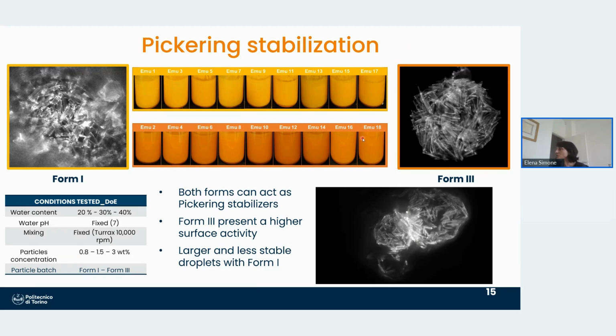And then again, Julia, now she's at the University of Leeds with a collaborator of mine in the physics department, Dr. Poncevic, and we're using light sheet microscopy to look at the position of the crystals at the interface. Form 3, as you can see, has a very nice affinity to the interface, also related to that specific contact angle. For form 1, now the image is not clear because what we think is happening is that some of the form 1 crystals are staying in the continuous phase.